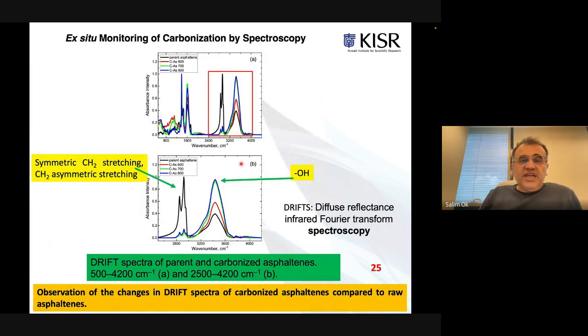When we monitored the carbonization by DRIFT spectroscopy, which is diffuse reflectance infrared Fourier transform spectroscopy, as you can see here, there is a reduction in the symmetric CH2 stretching and CH2 asymmetric stretching, which is a very nice indication of the carbonization. At the same time, there is an increase in the OH peak, as you can see here.